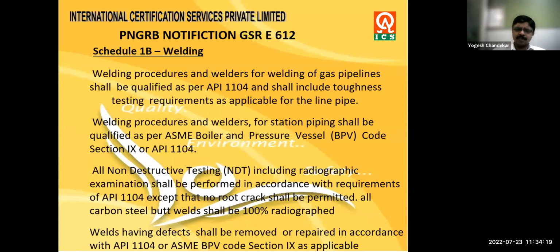And radiographic testing is done to check whether the joints are correctly welded or any defects are there in the welding joints. So that is verified by having the radiographic examination, and the acceptance criteria is as per API 1104, but no root cracks are permitted. So cracks are not at all permitted. For the other defects, API 1104 has given the acceptance criteria for each defect. So you have to refer to that and accept or reject based on the radiographic film interpretation.